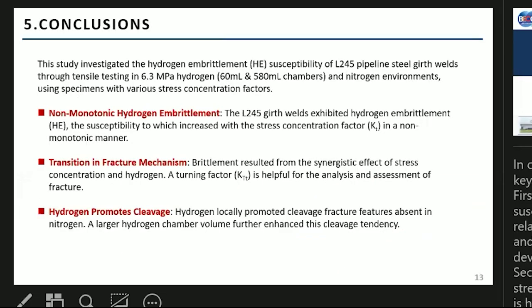In conclusion, our study reveals three key takeaways. First, hydrogen embrittlement susceptibility has a non-monotonic relation with stress concentration, and a critical factor may be crucial for developing defect acceptance rules. And second, embrittlement is a synergy of stress and hydrogen. A turning factor is helpful for analysis and assessment of fracture. And third, hydrogen locally promotes cleavage. Larger hydrogen chamber volume further enhances this cleavage tendency.